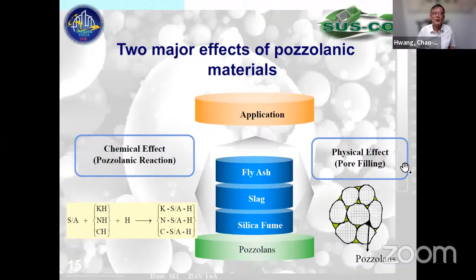not by replacement. No, we don't replace cement, because cement is cement. What we are doing is filling the pores of sand, because with the particle size we can fill the small voids. By looking at the physical particle size distribution, we know that this material actually has good gradation, so when you put it into the voids, it can stop any penetration of water. That is from the physical pore-filling effect.